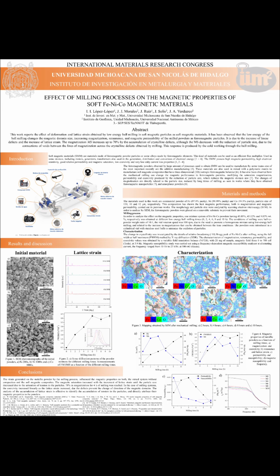It has been reported that in the iron, nickel, cobalt system, magnetization increases during the first step of milling, but the phenomenon is not clearly understood yet. In another study carried out on ferromagnetic hard alloys, it has been observed that the increment of such properties is related to the accumulation of defects that change the magnetic domain size. This can be attributed to the lattice strain during the milling process.